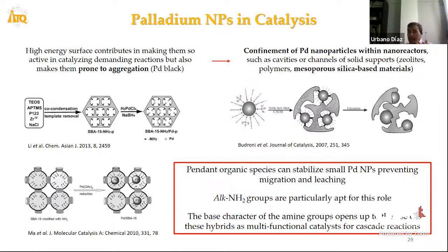But if the size of the internal pores is suitable, it's possible to avoid the aggregation of these metallic nanoparticles, even metallic clusters, in the internal pore volume of this type of materials, even with pendant organic species present on the surface of these materials. It's possible to prevent the migration and leaching of the metallic nanoparticles or clusters. And also these pendant groups can exhibit additional activity in the material, favoring the presence of two active sites at the same time in the same solid.